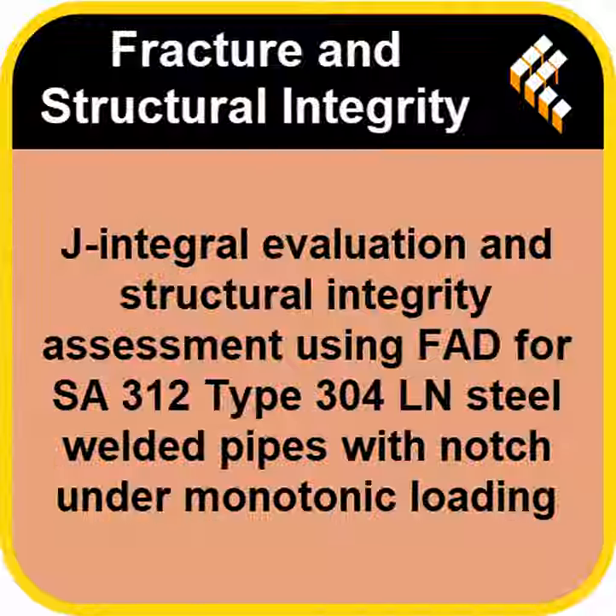Makes sense. And the specs, they really emphasize the real-world scale of this testing. The nominal outer diameters of these pipes varied significantly, from about 168 millimeters up to a massive 325 millimeters. Wow, okay. Big difference. Yeah, ensuring the results weren't just specific to one pipe size. And the artificial notch lengths were substantial too, going up to 170 millimeters. That's a very large flaw to assess.